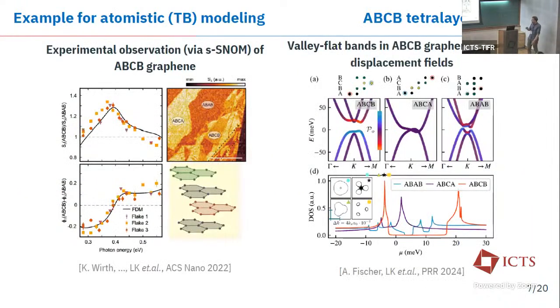And one example I want to bring up where we were successful in doing the atomistic modeling of those structures is the discovery of ABCB stacked tetralayer graphene. Recently, the experimental group at Aachen University discovered that they can see ABCB stacked tetralayer graphene using scanning near-field optical microscopy. And we did some atomistic simulations that confirm the optical conductivity and strongly confirm that this is going to be this type of stacking.